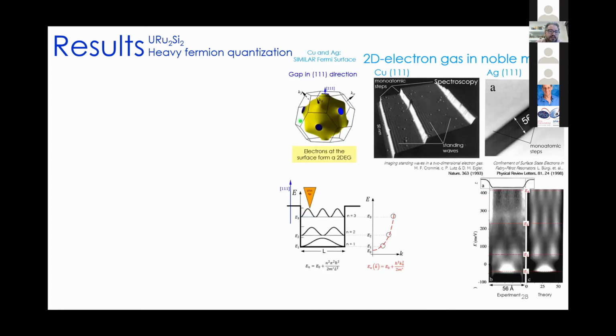So let me explain a little bit with more detail what happened here in the previous reports. The standing wave patterns are evidence of a two-dimensional electron gas. The two-dimensional electron gas occurs on surfaces of metals perpendicular to the directions where the Fermi surface has gaps. In the case of copper and silver, here we have the Fermi surface, and you can see here that we have a special gap in this direction, parallel to the direction that we are measuring with the STM. So from the analysis of the density of the states at each energy, we can see that this behavior corresponds closely to the physics that we have of an electron confined in a box of length L.